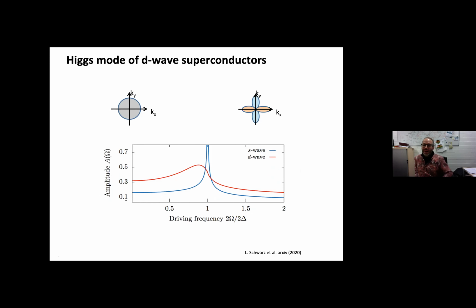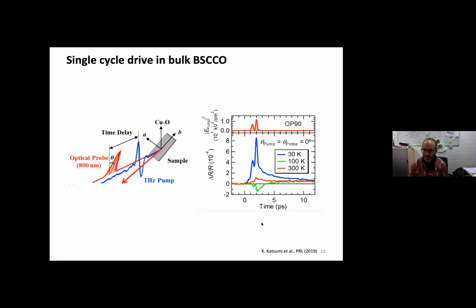And one way out is to drive these Higgs modes in the system. So instead of quenching the condensate, we will use the second approach to constantly drive the superconducting Higgs modes with a multi-cycle pulse. And there we also expect to see now, instead of this sharp resonance, something that is heavily smeared out due to the damping of the quasi-particles. At least if we look at this in theoretical evaluation of Higgs mode response within this pseudo-spin model that I've described in the beginning.